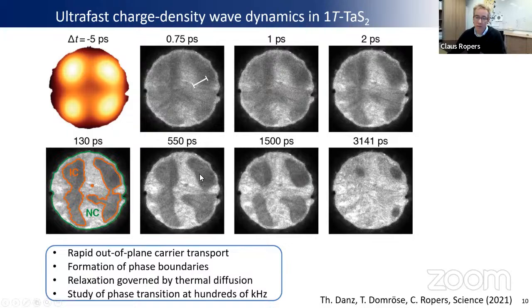There's a number of things we can extract from these. One of the things you might immediately see is that there's a relatively global suppression of the intensity at very early times and somewhat gradual transitions of the intensity over here, whereas at later times, one actually has relatively well-defined phase boundaries between these phases. So what this corresponds to is essentially the initial optical excitation suppresses the charge density wave and the periodic lattice distortion almost everywhere in the material, as in the diffraction data I showed a slide earlier.